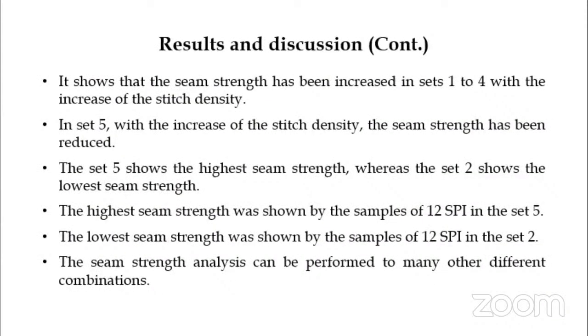It shows that the seam strength has been increased in set 1 to 4 with the increase of the stitch density. In set 5, with the increase of the stitch density, the seam strength has been reduced. The set 5 shows the highest seam strength, whereas the set 2 shows the lowest seam strength. The highest seam strength was shown by the samples of 12 SPI in the set 5. The lowest seam strength was shown by the samples of 12 SPI in the set 2. The seam strength analysis can be performed to many other different combinations.